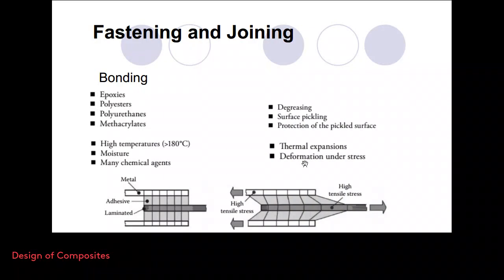In the hardware shop they tell you that you mix 1:1, but simply by varying the amount of curing agent you can play with the mechanical properties of the adhesive layer of the epoxy. So increasing the amount of curing agent will make it harder, but less strong. Decreasing the amount of curing agent will decrease the stiffness, so the bond will be elastic, in case of an epoxy. But on the other hand, it will be less strong, let's say, we can say that.